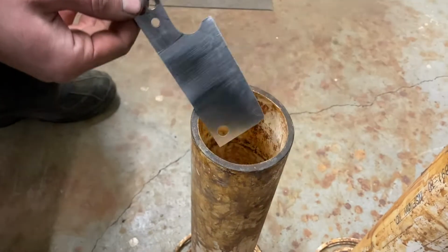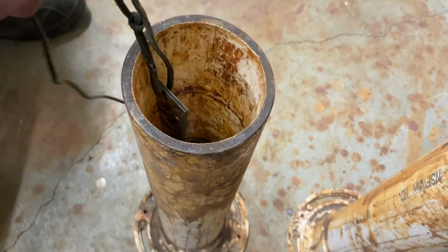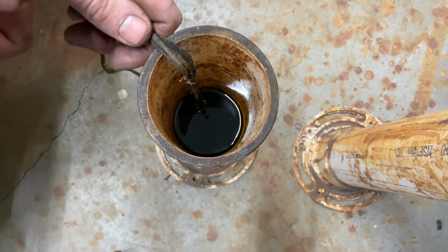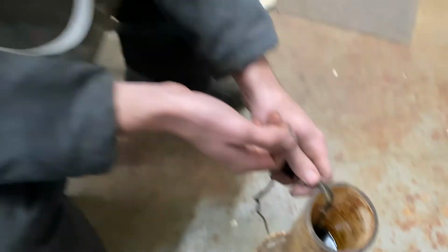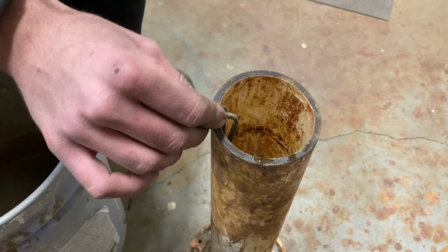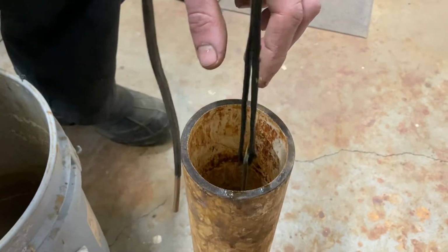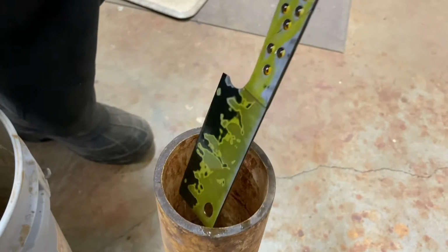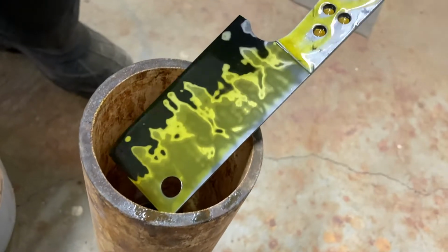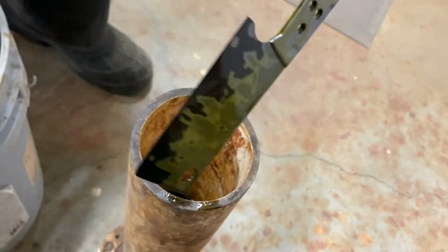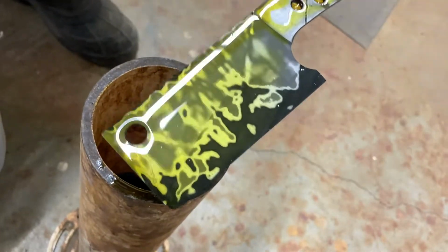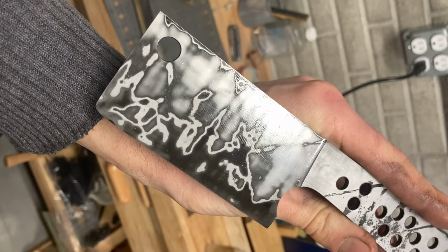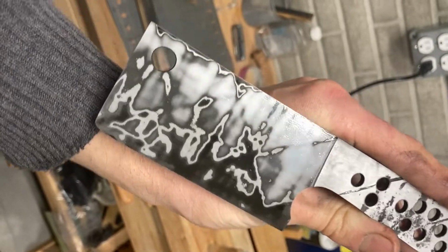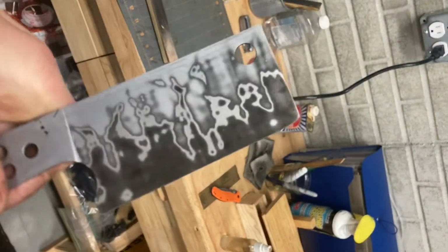Into the ferric chloride acid we go. I'll leave it in there for around 5 minutes just to get some depth and color. And my favorite part, seeing the pattern revealed. After that, I just neutralize it with some baking soda water and then put a light coating of oil on it.